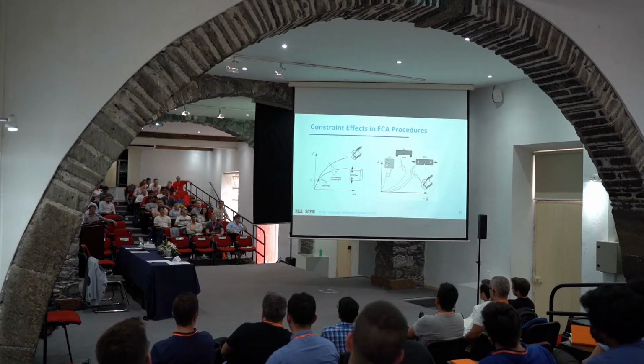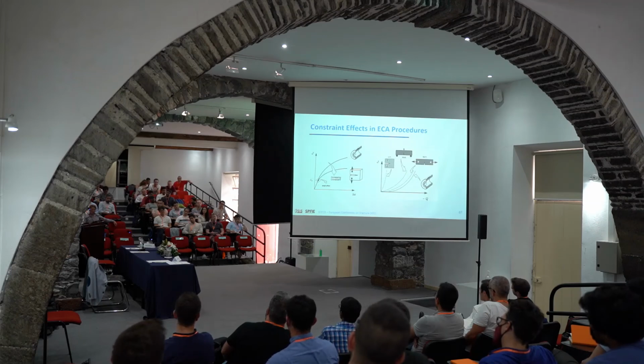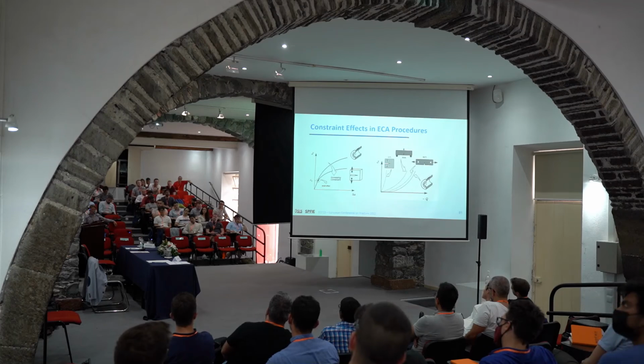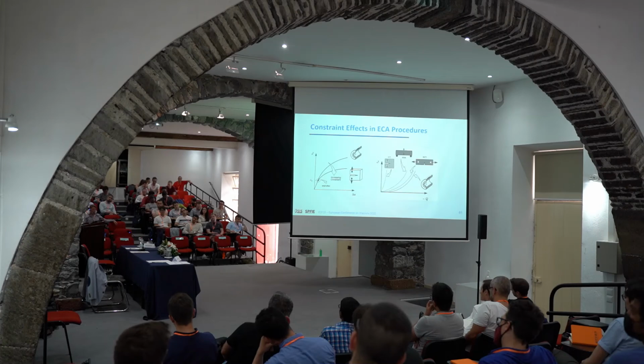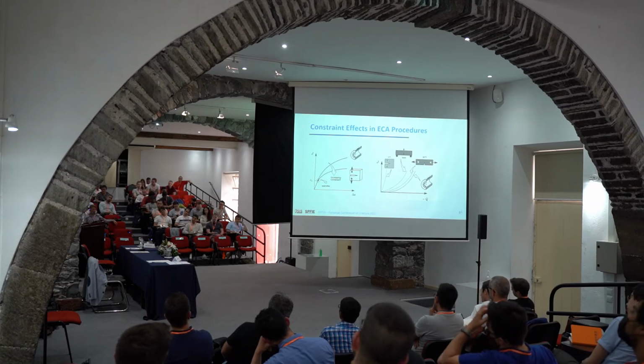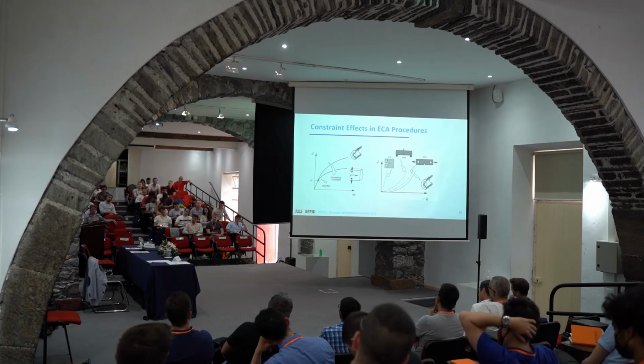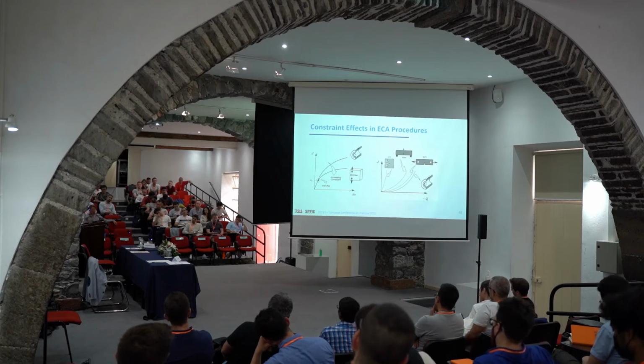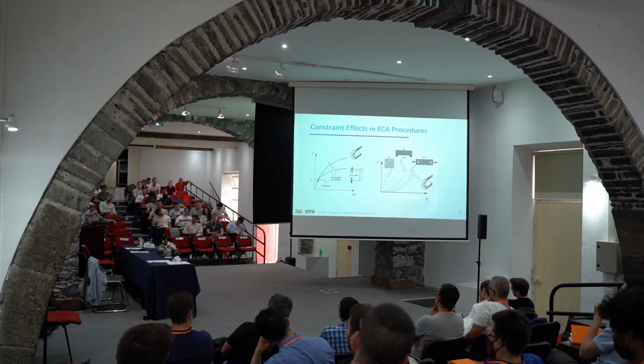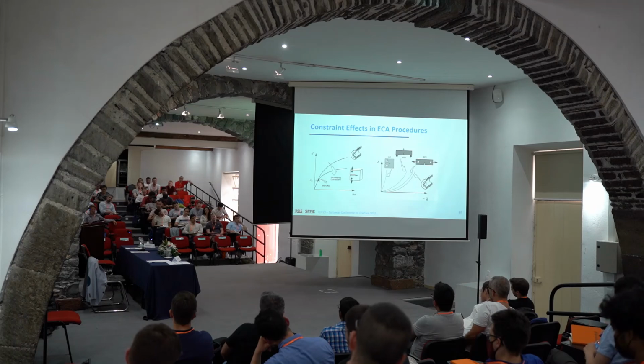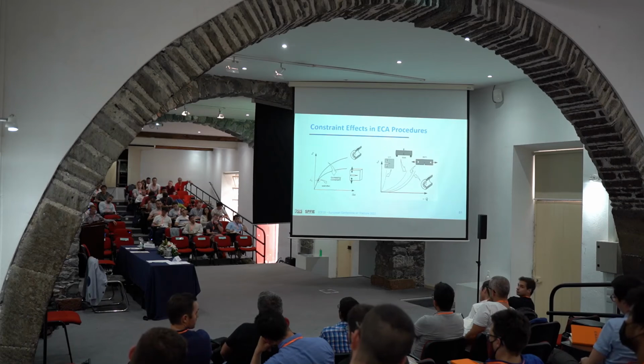When you use J or CTOD to characterize your fracture behavior, what you are actually saying is, if you have a J value of, let's say, 50 kilojoules per square meter, or megapascal millimeter, that means that implicitly you are defining the crack tip stress fields. When I say that the J integral that describes the fracture is 50, I'm actually saying that I know, implicitly, the stress fields which are driving fracture. You are not measuring them, but implicitly you are defining the stresses that control fracture. This works very well. We call this single parameter fracture mechanics, because you use only one parameter: K for linear elastic, and J and CTOD for elastic plastic.